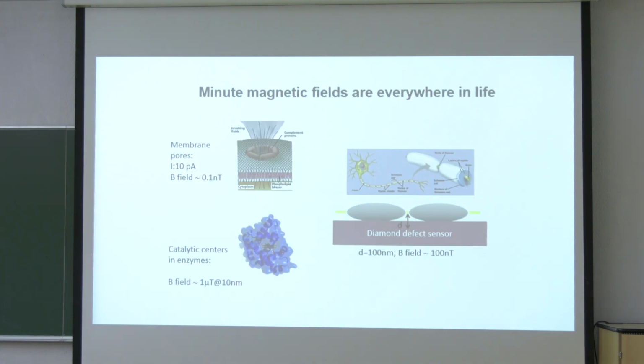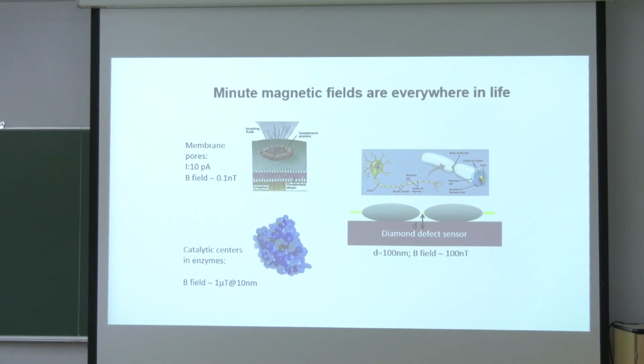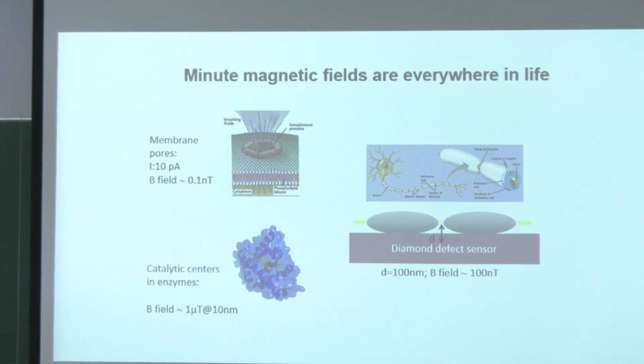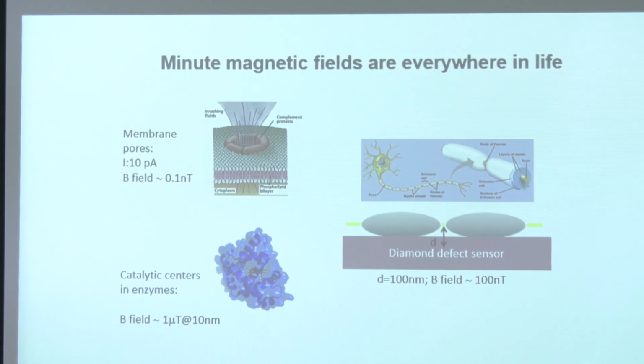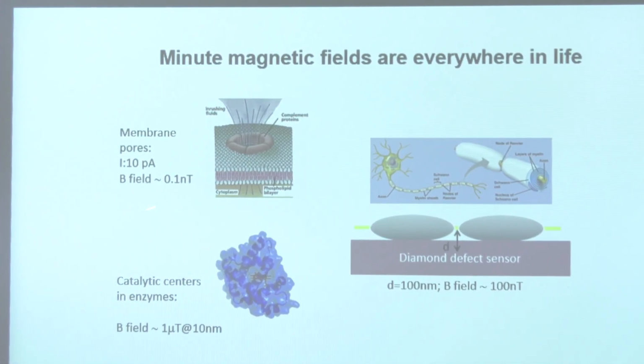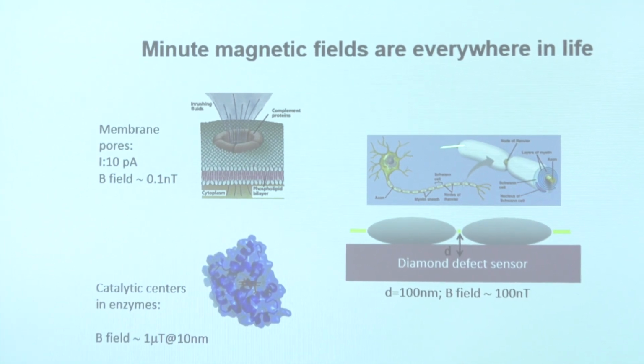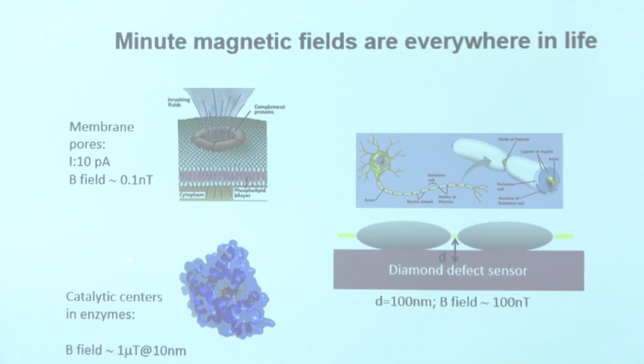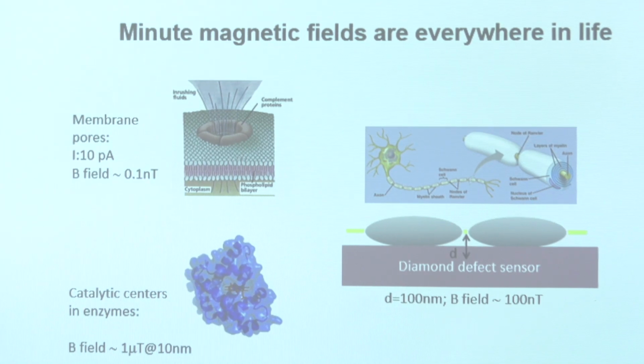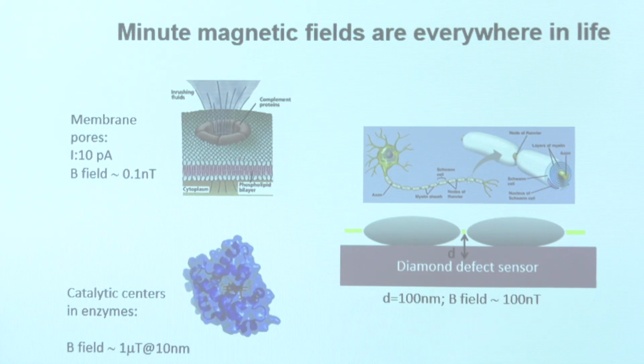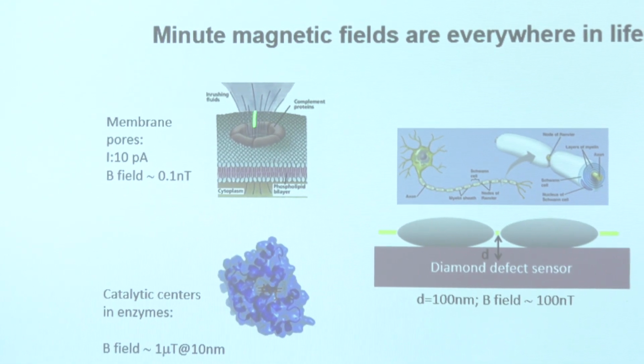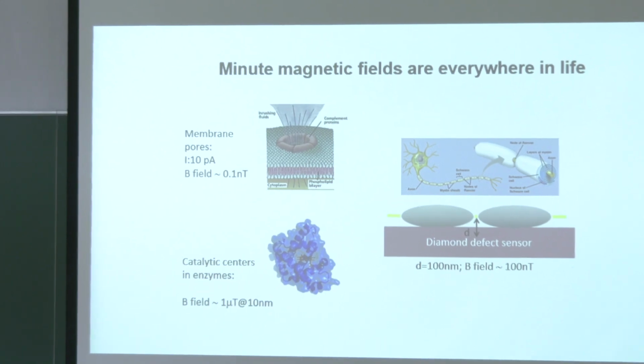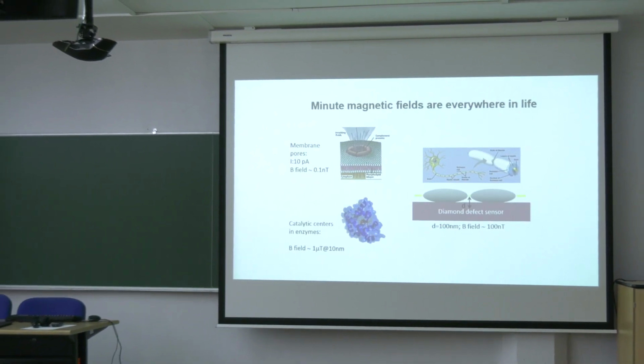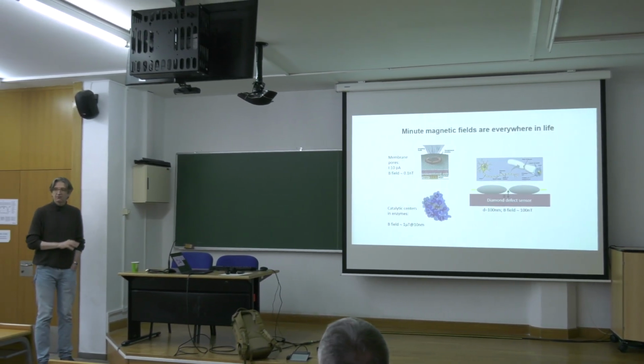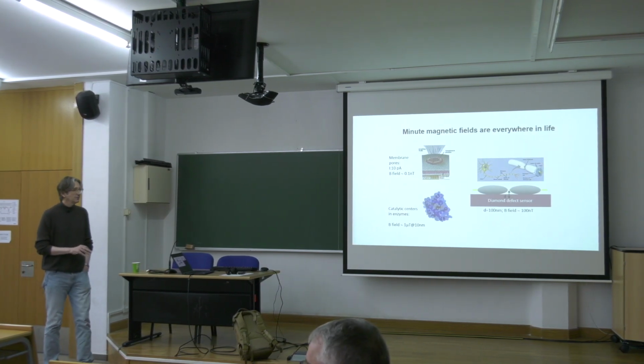I was focusing more now on NMR, but NMR is not the only field where these qubits can be applied. If you are talking about magnetic fields and think about life, there are many processes in life where magnetic fields are involved. If ions pass through channels, like for example calcium ions in neurons flowing through channels and inducing the action potential, they introduce a current of about 10 picoamperes, and if you're very close to the channel, that corresponds to a field of about 100 picotesla. So that's something not very far from what we can measure with NV centers.